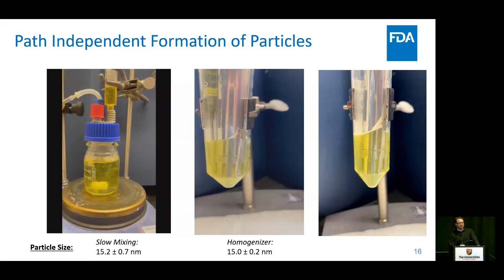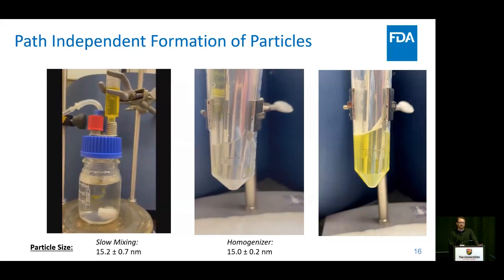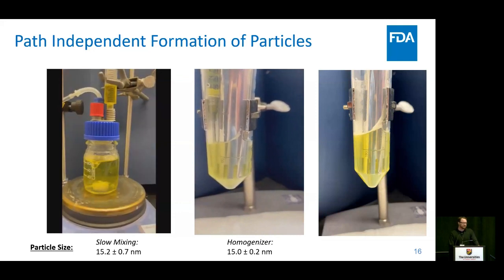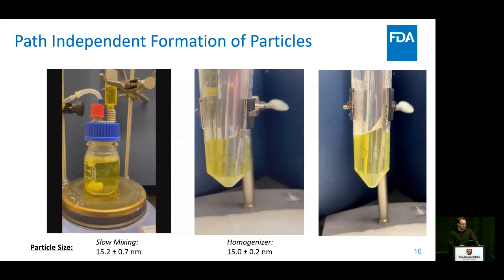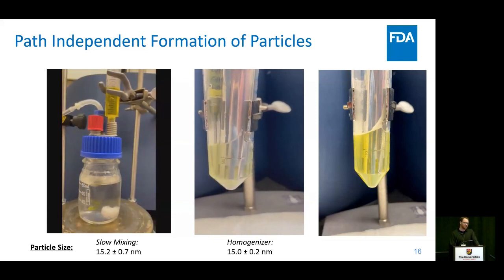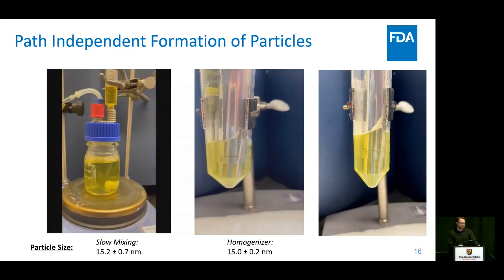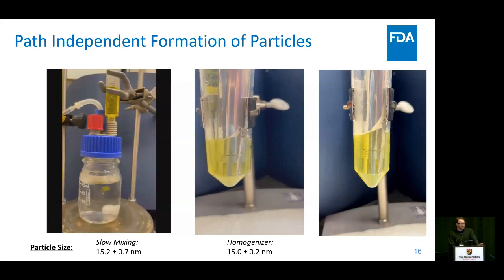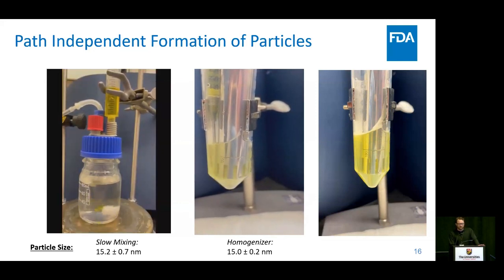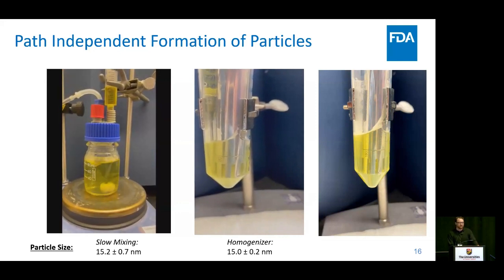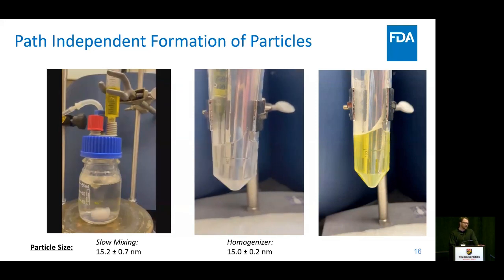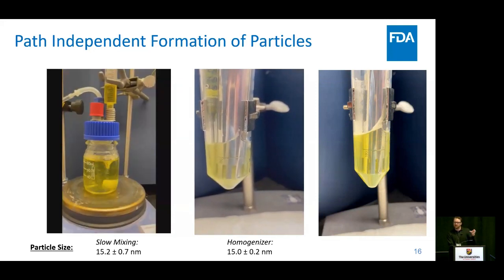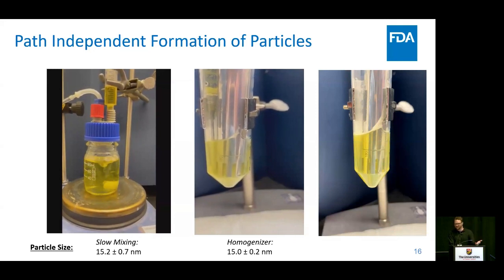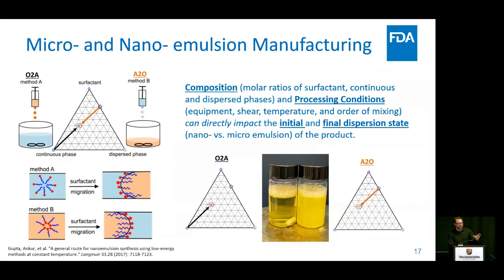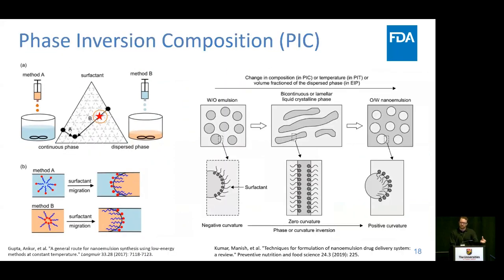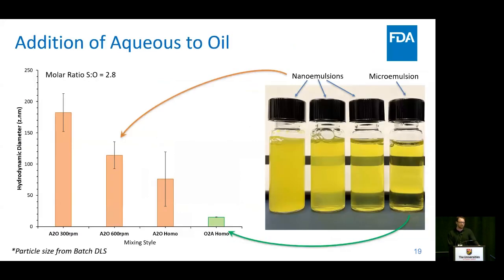We have the same composition. We can use different shear rates in order to induce different amounts of particle size formation and different amounts of particles ranging from about 200 to 100 nanometers, as well as our microemulsion we formed using the other directionality. And so if this is truly a microemulsion, you should be able to take two separated phases, and over time, given enough energy, they will form the microemulsion. If you have a nanoemulsion or a true emulsion, just like salad dressing, if you put it in your refrigerator, given enough time, it phase separates. So if we were to take the nanoemulsions we produced, the question is, given enough time and energy, does it split or does it form a microemulsion?